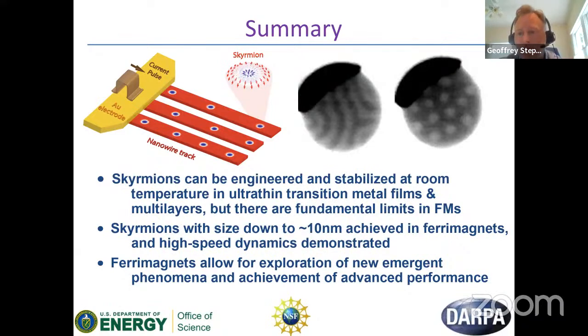For the DMI, however, we believe that is something that is more intrinsic. Again, we don't have something mechanistic, but the absence of the rare earth, we find that to be correlated with an absence of DMI. So with the bismuth YIG, for example, as you indicate, that has a magnetostriction that allows it to get PMA, but we don't see DMI no matter what metal we put on that material. And likewise for the temperature dependence, we find that the DMI in the rare earth containing iron garnet has a temperature dependence that tracks qualitatively the temperature dependence of the orbital moment of that rare earth. Okay. So thanks. Circumstantial, but that's simply the experimental results that we have at this point.